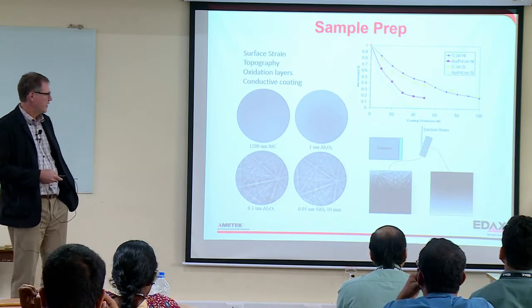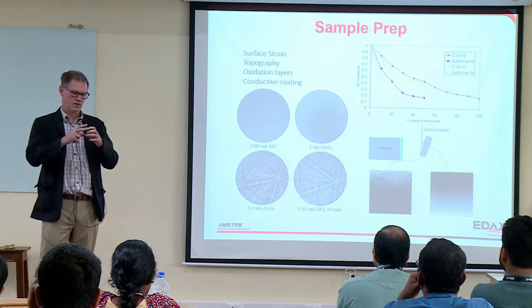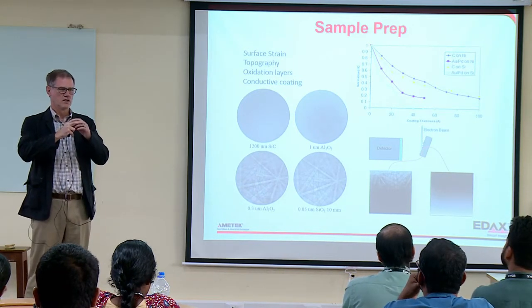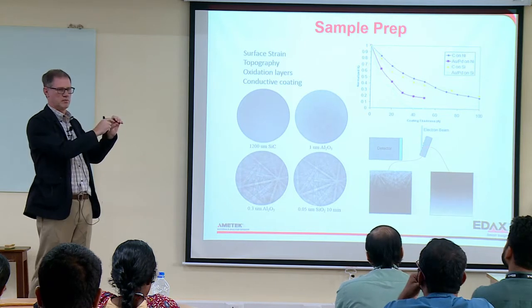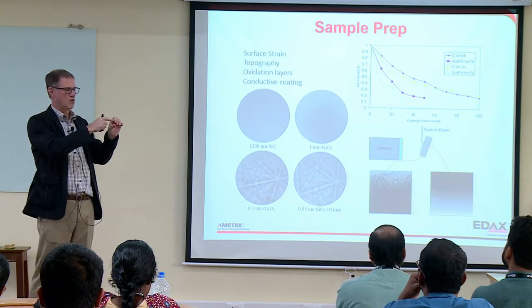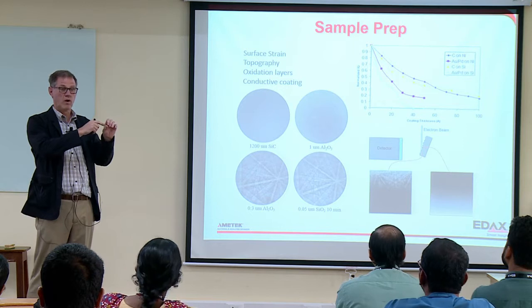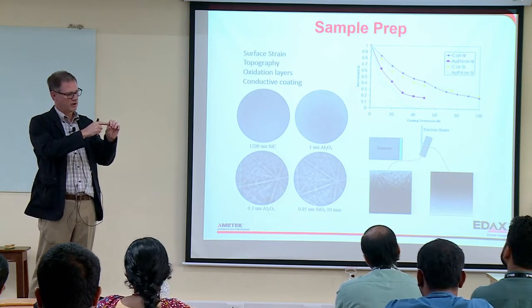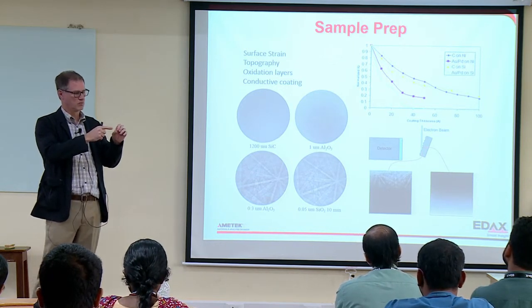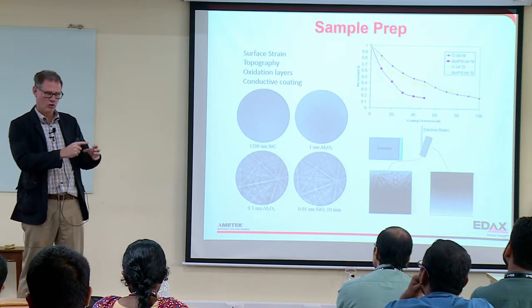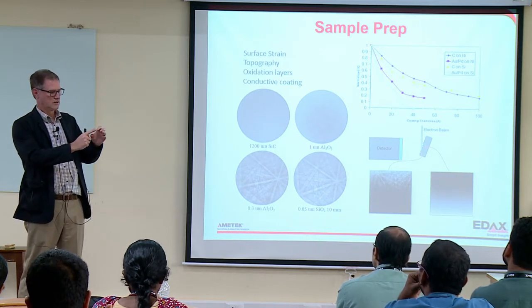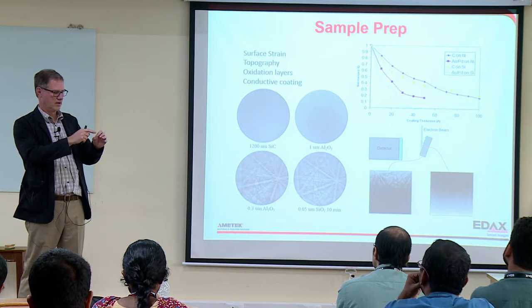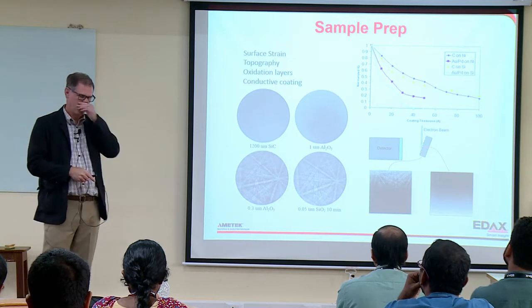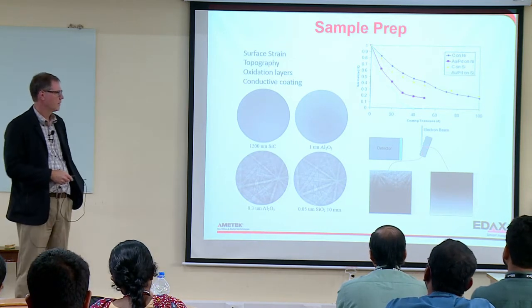What we've also found is that if you take a sample, so if you have it in a polishing disc of some kind and you have your samples right in the middle, it really makes sense to coat everything around your sample quite heavily and then just coat very thinly over your sample. So what we'll do is we'll do a thin coating over the whole puck or disc, and then just paint by hand around the sample with silver paint. That seems to work well.